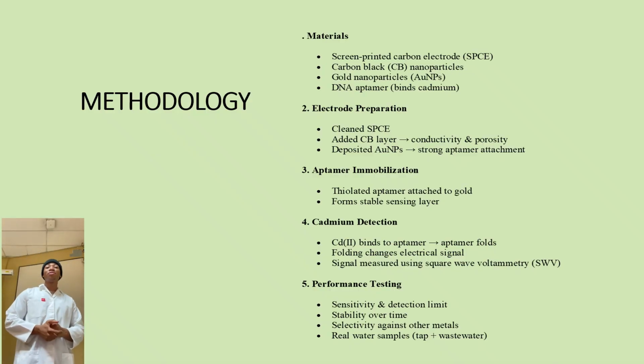I'll briefly explain the methodology of the research. The researchers aimed to build a simple and sensitive sensor to detect cadmium in water. First, they prepared the base electrode, which was a screen-printed carbon electrode. They improved it by adding carbon black to increase the conductivity and porosity, and then deposited gold nanoparticles on top.